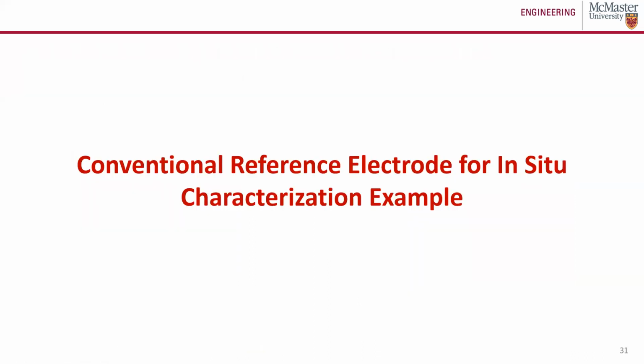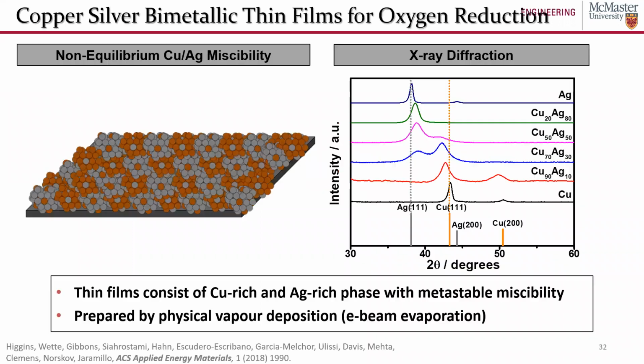So now let's just give a practical example of when a conventional reference electrode could be used for in situ characterization of materials. During my postdoctoral research, we were developing these copper silver thin films, and we found using X-ray diffraction that it was a multi-phase system consisting of copper rich regions with silver atoms sprinkled within it, and then silver rich regions that had a few copper atoms within them. So we call these our metastable phase segregated materials.